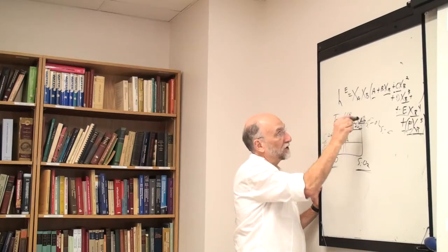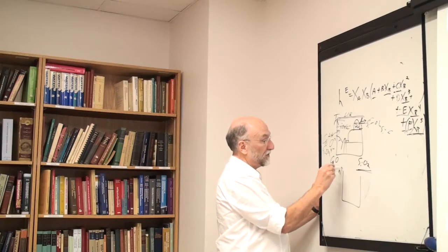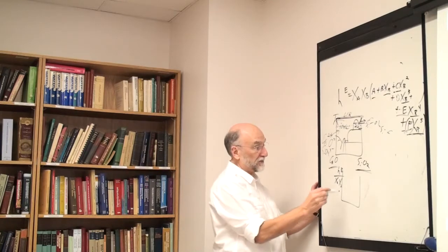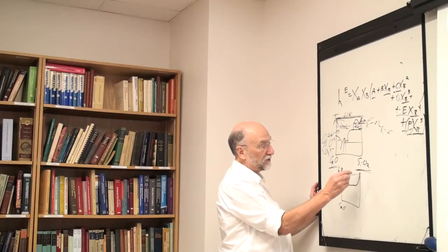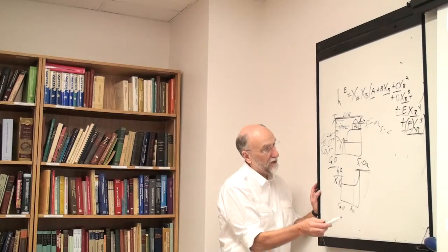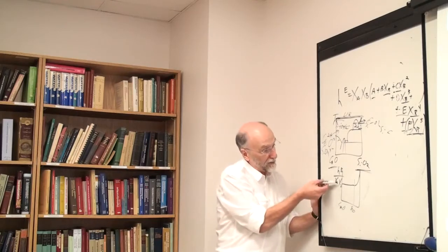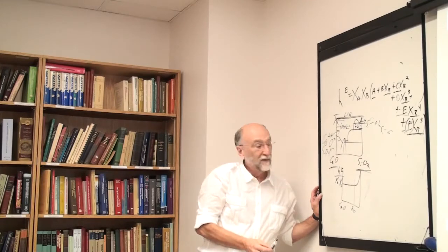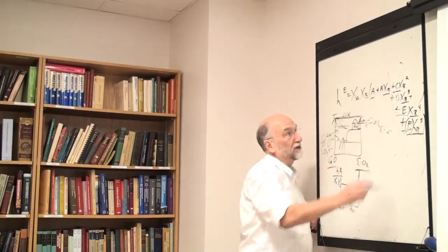And as you're going across here above the 2-liquid region, what we'll find is if we were to plot, say, the enthalpy of mixing divided by x1 x2 versus composition, going across the liquid in such a system, we would find it remains pretty much constant, and then goes up very, very steeply at the end, after about 80% or so. So in other words, this is very much something that is fitted with this type of function. It's something that remains more or less constant and then changes very rapidly as you get to pure silica. That is then the form of the function you're trying to fit, and we find then that you're actually better to fit it with this kind of expression.